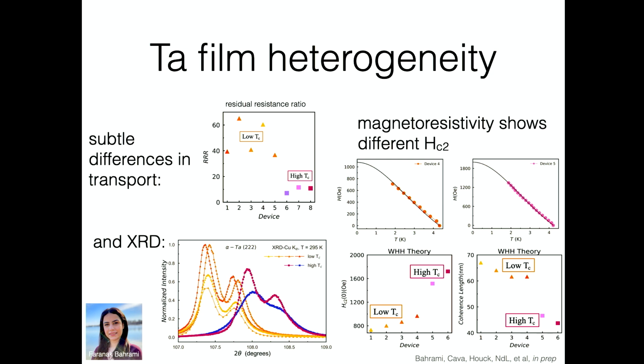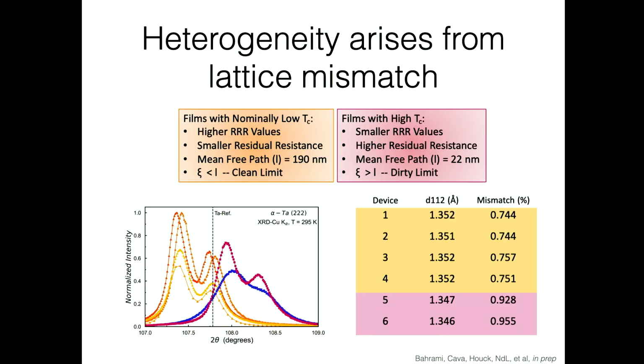We also could see a different critical field if we did magnetoresistivity measurements. And then if you did a really careful job of your XRD and calibrated it properly, we could actually see a shift between these two different populations of something like half an angstrom, 0.16 angstroms. And okay, so there were clearly differences, and there's sort of a hint already in all of this data about what the differences are. So these XRD peaks look a lot messier and kind of broader. So the good films have more disorder. Again, a weird thing for material scientists.